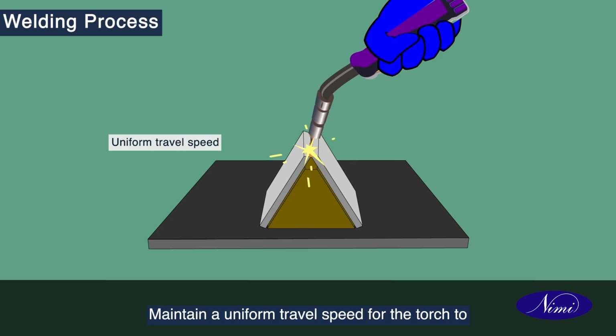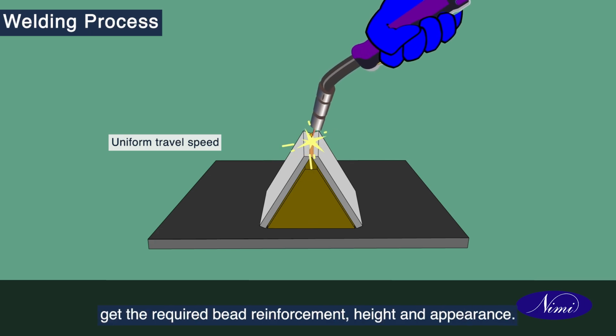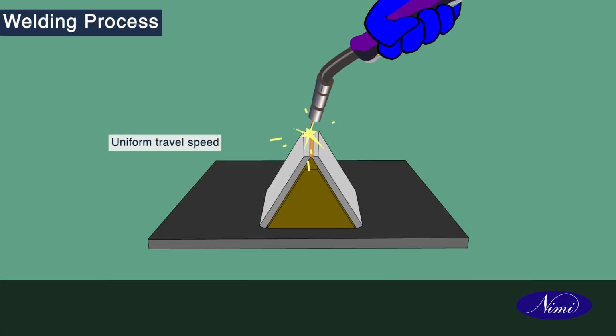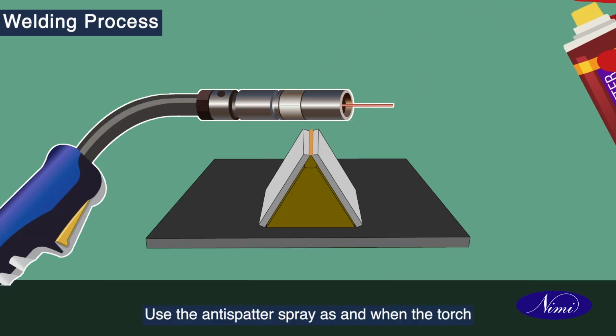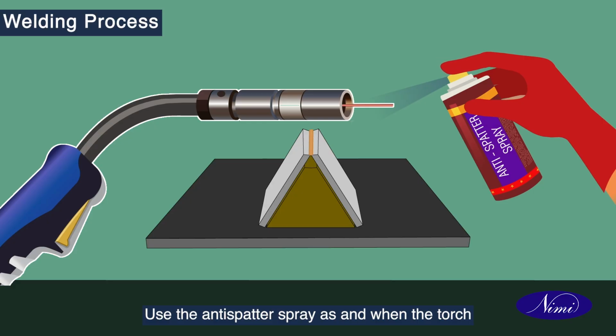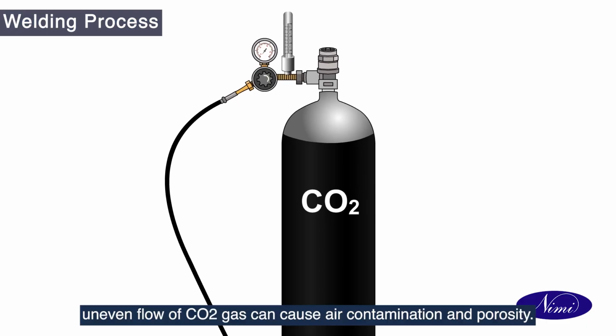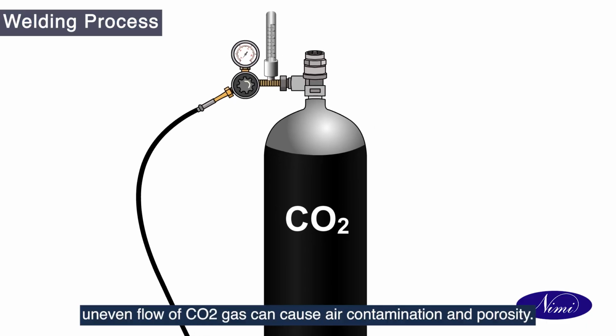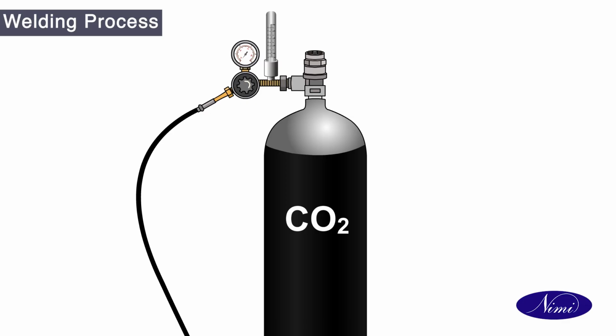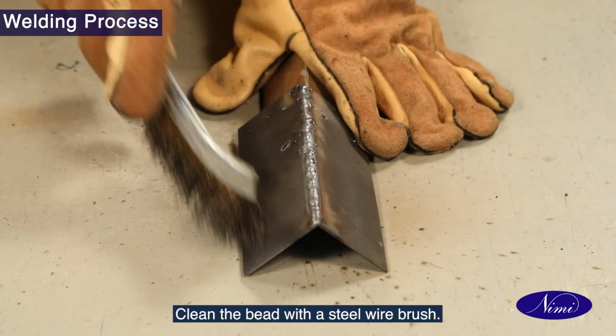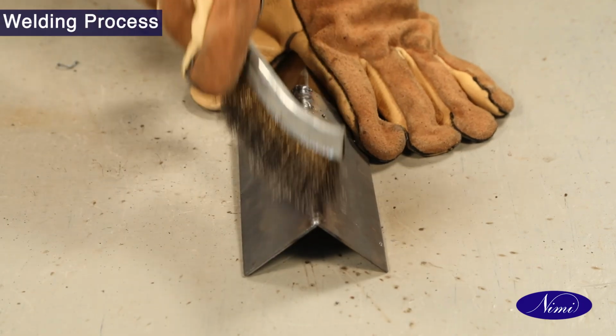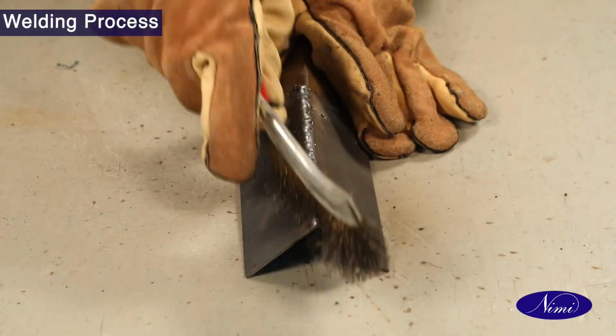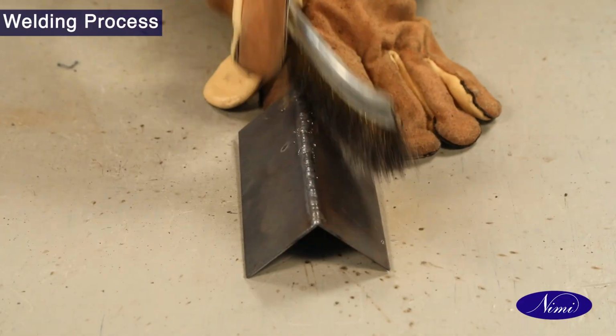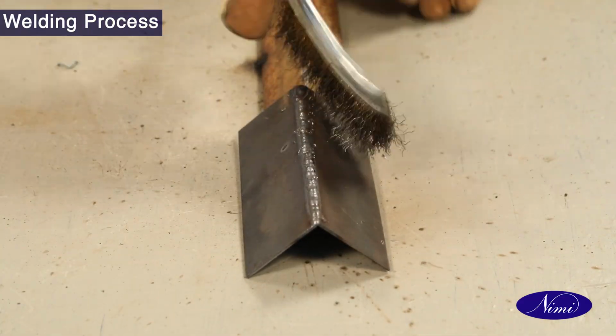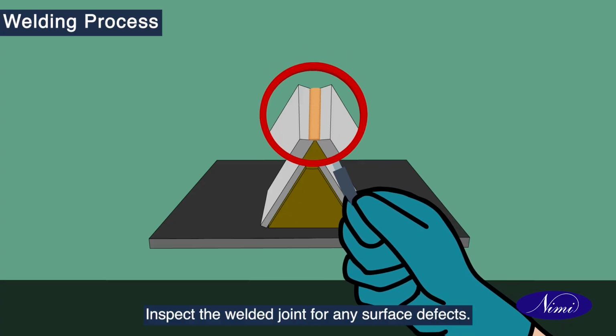Maintain a uniform travel speed for the torch to get the required bead reinforcement, height, and appearance. Use the anti-spatter spray as and when the torch nozzle gets clogged with weld spatters. Uneven flow of CO2 gas can cause air contamination and porosity. Clean the bead with a steel wire brush. Inspect the welded joint for any surface defects.